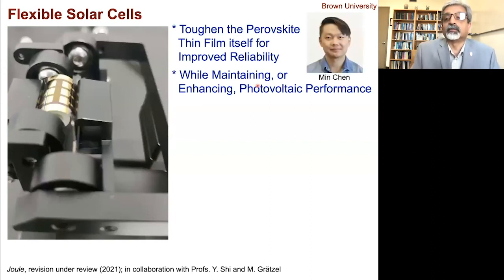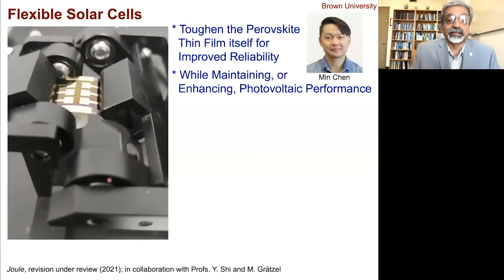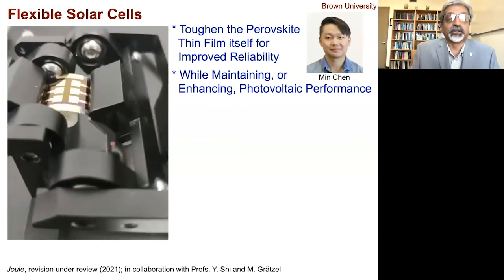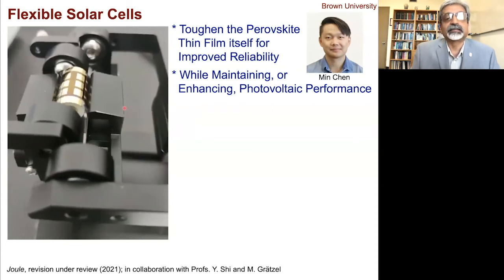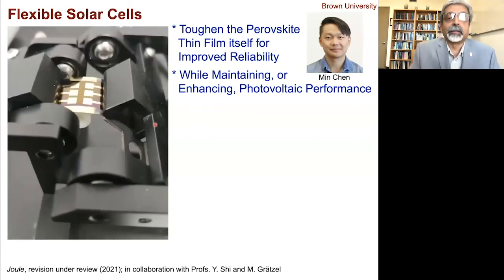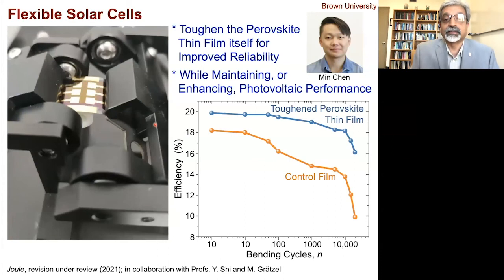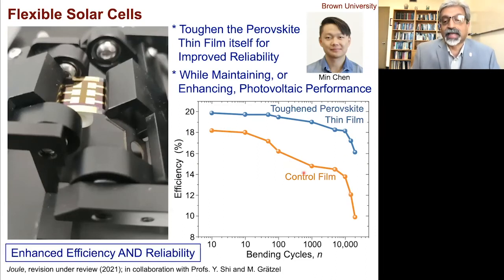And this is the work of my PhD student, Min Chen. And this is a testing device that he has. It basically shows fatigue testing of these solar cells, right? And this is the data. So this is actually absolute efficiency. You can see the efficiency has been improved from control to this toughened perovskite thin film, and it lasts more than 10,000 cycles without degrading as much as the control film. So this basically shows you enhanced efficiency and reliability in these approaches.